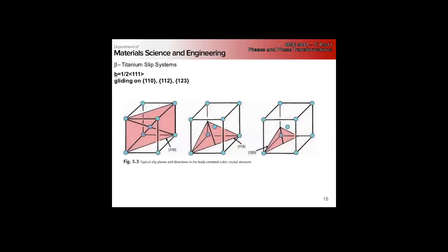So relative to steel, what can we expect the ductility of titanium to be? For BCC it's pretty comparable. Oh, really? Yeah. So if you're in a beta alloy, you can get fairly significant ductility. In many cases, you can potentially get a lot more ductility because you don't have the carbides that act as fracture initiation sites, right? But BCC materials in general can be very ductile. What about the alpha? Once you have significant alpha plus beta, you're going to have less ductility, right? Which causes a lot of problems.